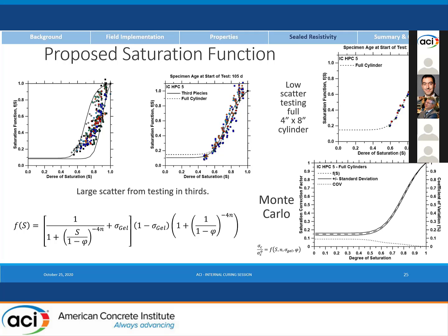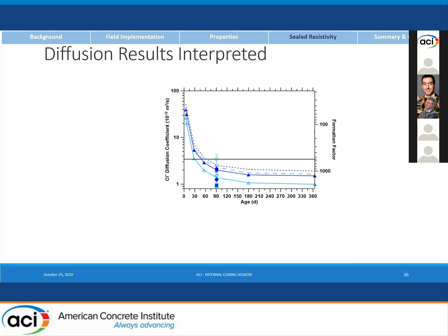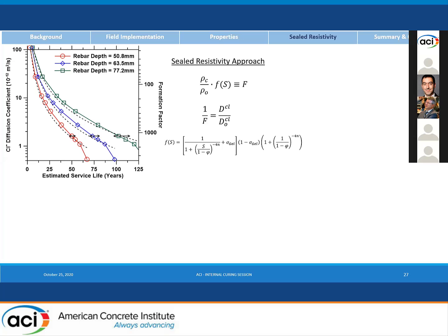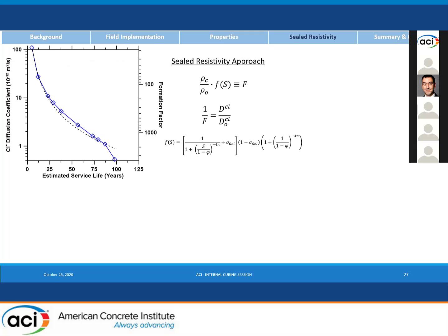And then you can apply some statistics to it, and we can come up with an actual coefficient of variation within the testing method. And so when we put all that together, we can turn this around and say, well, now I have a target diffusion coefficient that I'm looking at, and we can evaluate relative to that. If we go through and start with service life estimations, and begin varying what the chloride diffusion coefficient is, we can create these kind of response maps in terms of estimated service life. So we can see what the variation from north to south in the state of Indiana might look like, the variation for construction tolerances for the steel depth, and then perhaps a 20% variation just on the actual measurement itself.